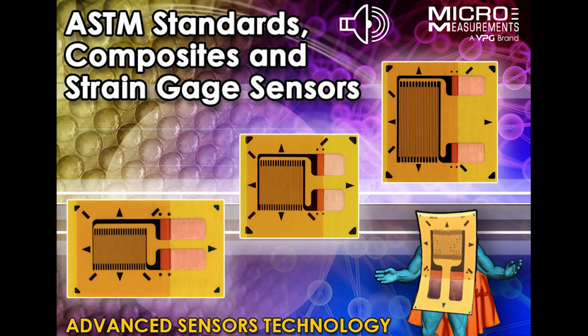If you're just looking for the shear modulus in the direction you're pulling, then a 187UW will work. But in a lot of cases, again, the ASTM is very specific. Stay within 350 ohm, and sometimes you can go to 500 ohms. Like with the D5379, this is a 500 ohm gauge designed by Micromeasurement to do the test. It's much better.